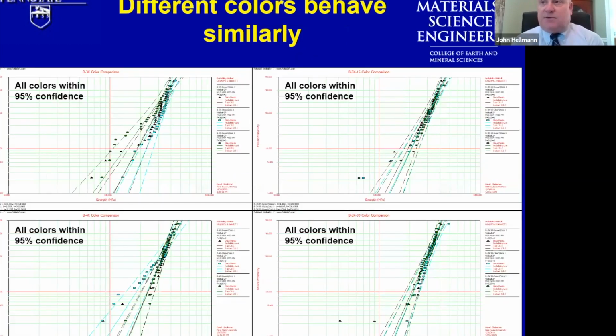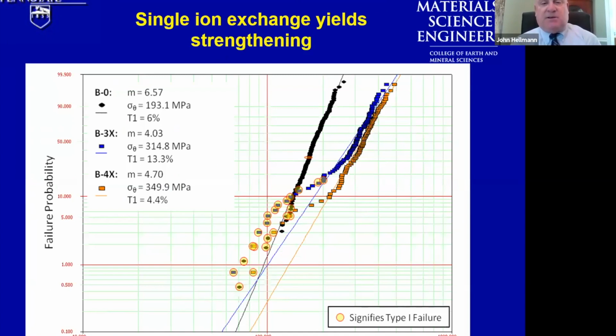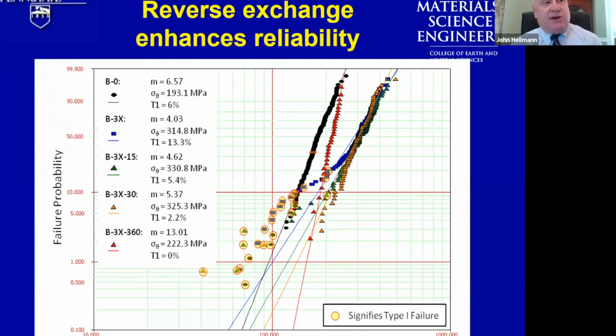We found that colors behave similarly. There was no difference. We don't need to separate the different colored glasses for this application. And that single ion exchange yielded strengthening as was expected. And reverse ion exchange enhanced the reliability, also as we originally hypothesized and has been seen on other types of